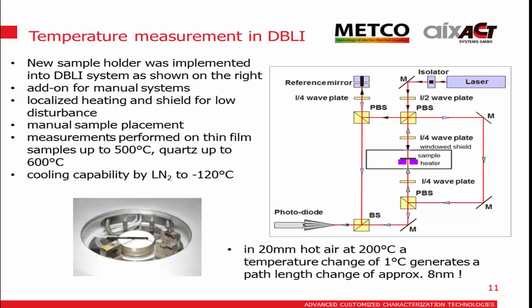But for a typical PZT film, it's like 5 nanometers, in this order of magnitude. So we have developed, within the project, a stage to go up to 600 degrees C, also being able to cool down in this environment.